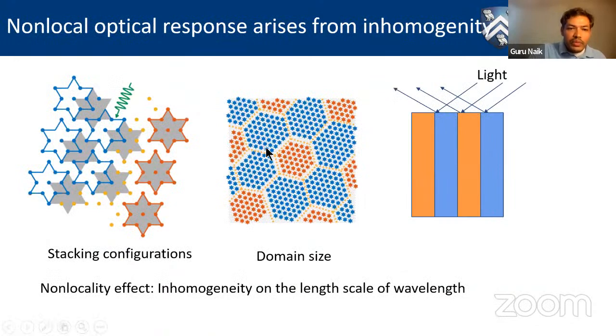So why? We have two different stackings, and this material is clearly inhomogeneous. And if this inhomogeneity is on the order of the wavelength, we should expect non-local effects. Of course, charge density waves themselves behave with hydrodynamic behavior, and there is non-locality, which some papers have already talked about, and we're still not there to probe them. But clearly the stacking is one of them, which should be easy to probe. So that's where we began.